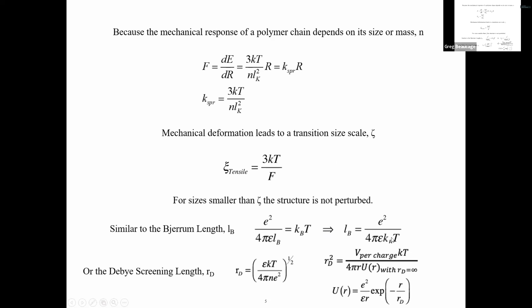And that also has something to do with KT, except here, the higher the temperature, the smaller the Bjerrum length, because KT kind of eats up the charges that are making things organized. Whereas here the length is proportional to KT, because the larger KT, you disorganize, you disrupt the lengthening of the chains.